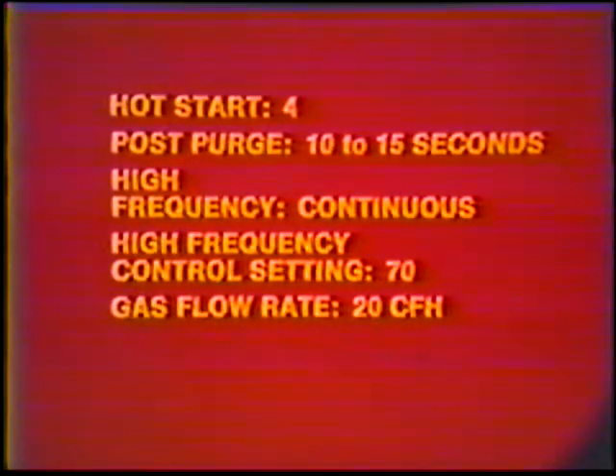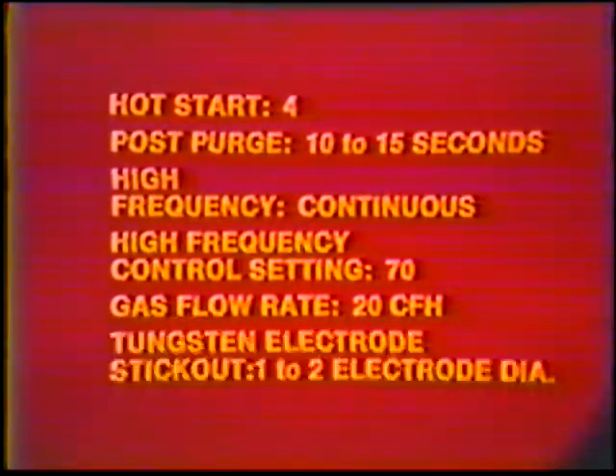Machine settings: current, AC, amperage setting, 140 to 150, weld current remote control, on, hot start, 4, post purge, 10 to 15 seconds, high frequency, continuous, high frequency control setting, 70, gas flow rate, 20 cubic feet per hour, tungsten electrode stick out, 1 to 2 electrode diameters.